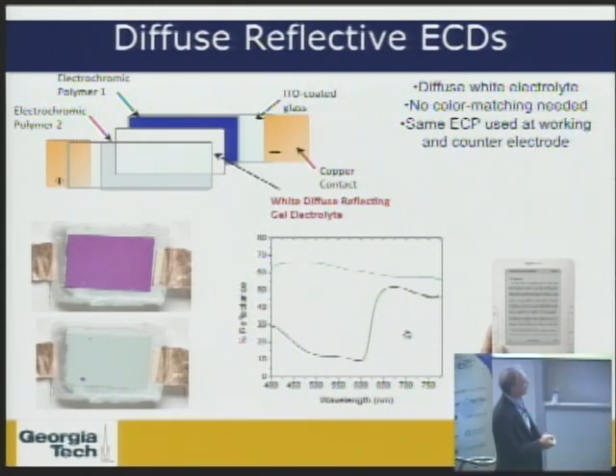And you're looking at that here in this photograph of the ECP-Magenta going from its colored state here, and then here you're looking through that polymer at the titania. And you can see from the reflectance data on the order of 50 to 60% reflectance through the entire visible range, a nice colored state in terms of 10% reflectance at this point. And in essence, what we have is a pixel that mimics that of an electrophoretic, but we have the ability to do this for all colors. As was mentioned this morning from the Boeing talk in terms of the possibility of changing colors on surfaces, in essence, you can mix these colors, you can create any colors you want, earth tone colors, etc.